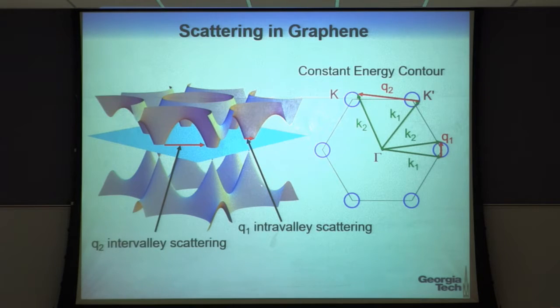This is the close-up of that energy structure again. Take a slice across here. So an electron at this energy, if it's elastic scattering, has to stay on that circle. And so it can scatter to any one of these other points on the circle. But the place it does it most is right across the circle where the regions are sort of parallel to one another, because that has the most connecting vectors, nesting vectors. So the nesting vectors basically are Q1 and Q2 in this system.